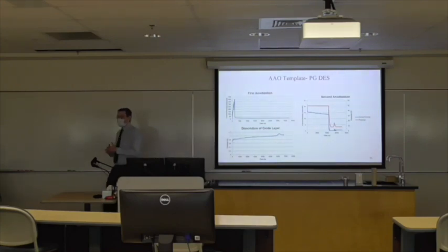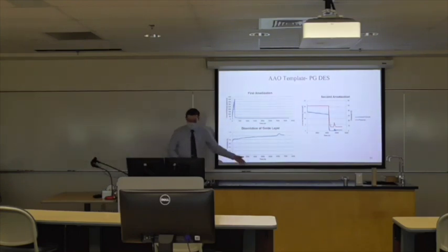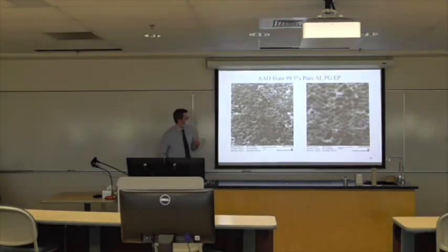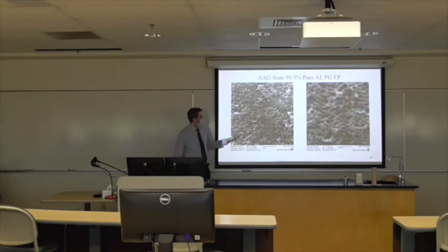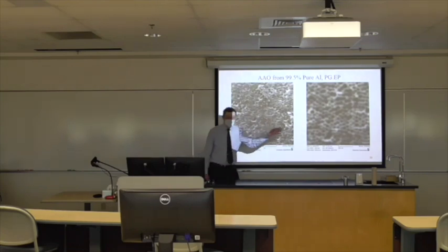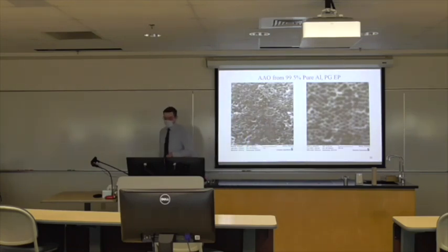So these things work very well with 99.99% pure aluminum. When we use less pure aluminum, we get these pores. Now, the pores are still worse looking, for sure. The oxide layer looks much worse. However, there's still the 60 nanometer pores that you can see in the oxide layer.